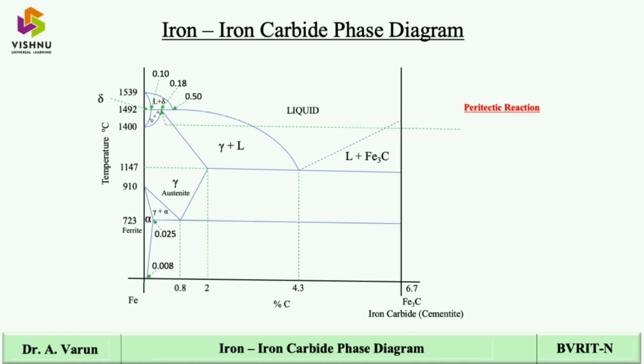This peritectic reaction occurs at this point here. So at 0.18% of carbon and 1492 degrees centigrade, the liquid plus delta iron will combine to form a new solid, which is called gamma iron. That is, liquid plus delta iron gives rise to austenite. This is our first invariant reaction occurring in the iron carbide phase diagram.